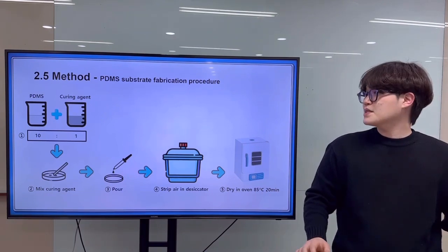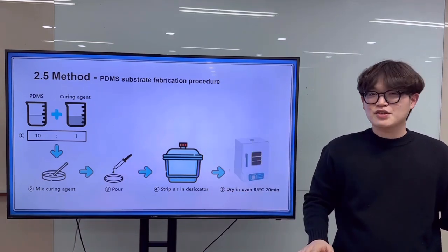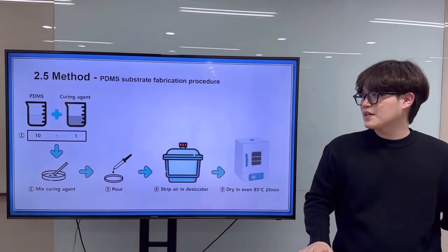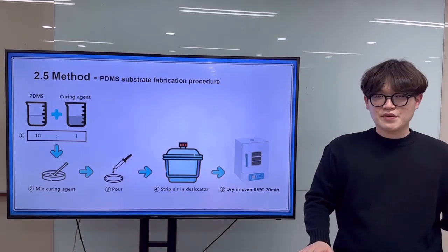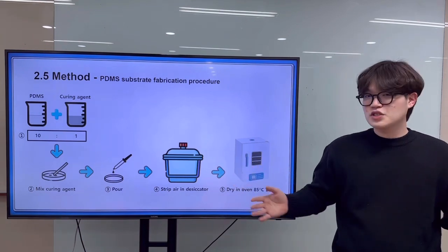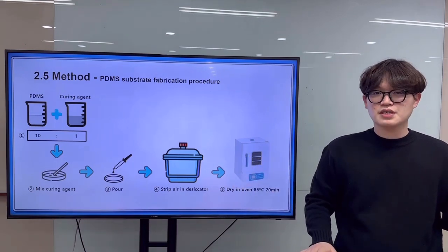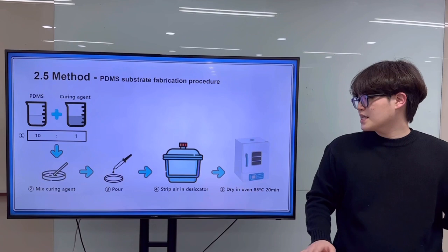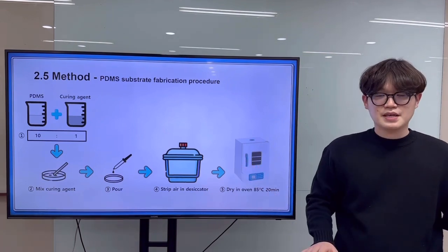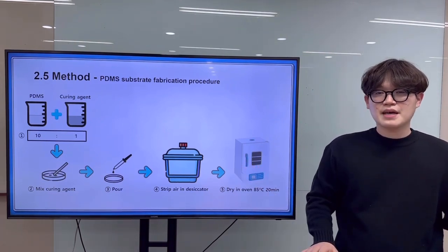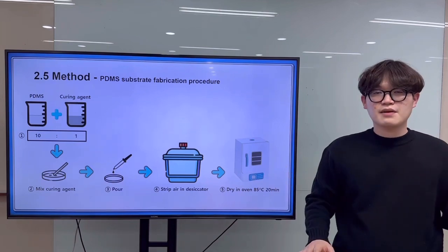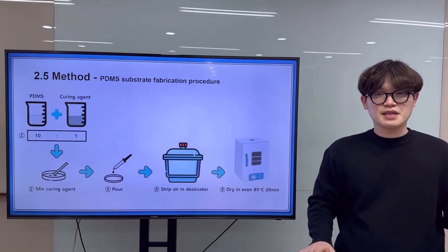So, first, mix PDMS with curing agent in a ratio of 10:1. After stirring, pour the solution in a Petri dish. Then we use a desiccator for air stripping. Finally, cure them in an oven at 85 degrees Celsius for about 20 minutes.